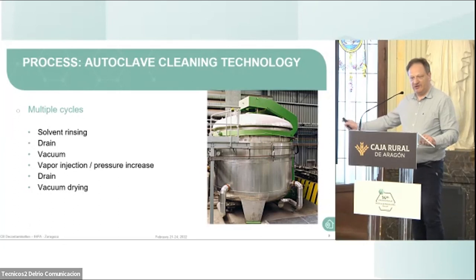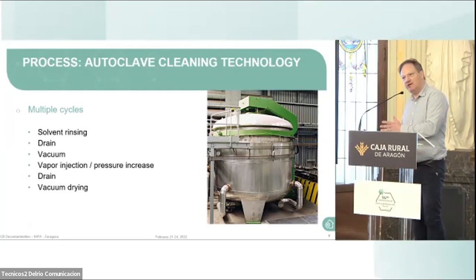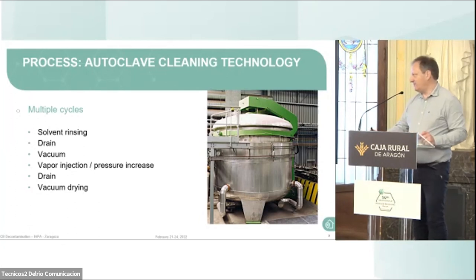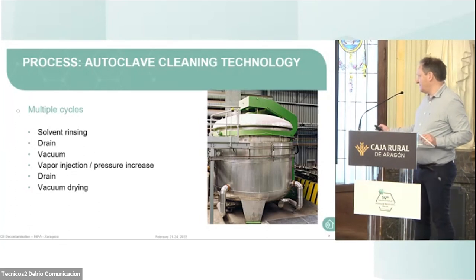In fact, what you see is only 10% of the installation. Behind the installation, you have a heating cooling unit. You have distillation equipment to recycle the solvent. You have a huge regenerated activated carbon filter to control the emissions. I just would like to say that this is not an easy installation just to make it mobile and put it somewhere in another country. So it's quite a complex installation.